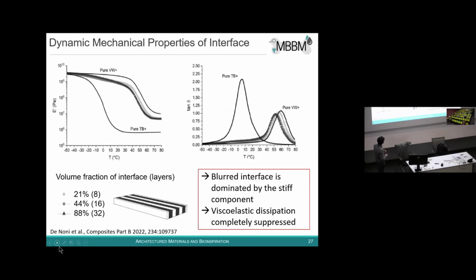And then we compared what is happening in these simple plate-like multi-layer samples when we have different amounts of interfaces due to different numbers of layers. And so what we see, to cut the story a little bit shorter, is that the interfaces, although you are mixing equal amounts of soft and hard polymers, are strongly dominated by the rigid component.